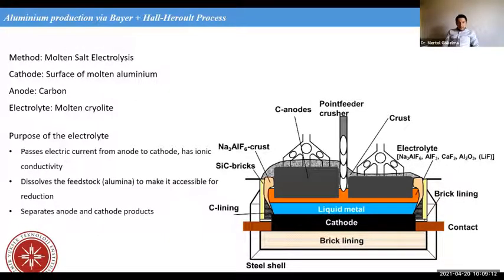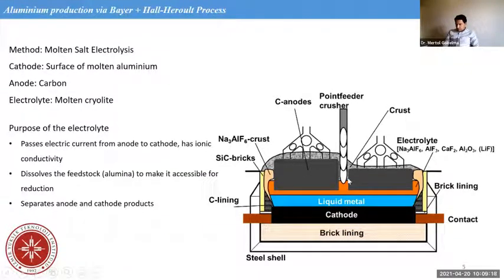In this case here, briefly, here we have the carbon anodes. I will show with the presenter laser. We see here the carbon anodes and the point feeder. We have here the crust of the electrolyte because of the radiation. Here we have solidification, but this is also an advantage sometimes because it reduces the radiation and the heat losses. And to avoid heat losses, we have silicon carbide bricks, carbon linings, brick lining, and the steel shell. And in the electrolyte,